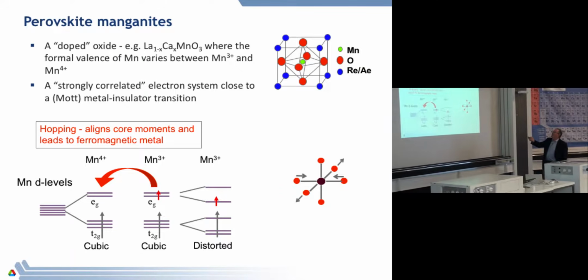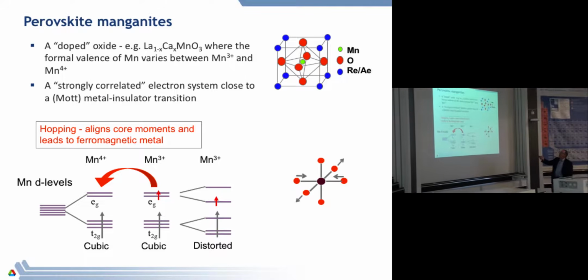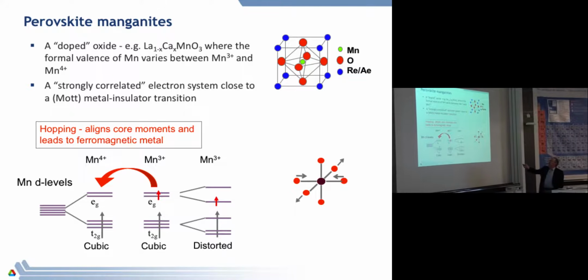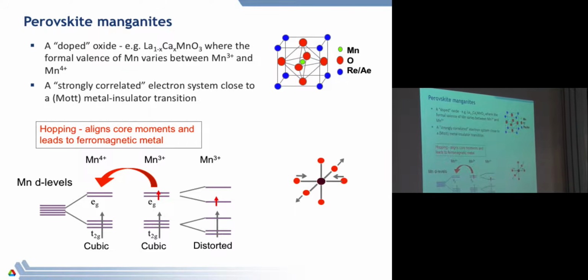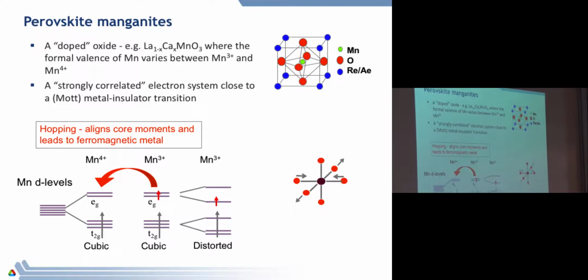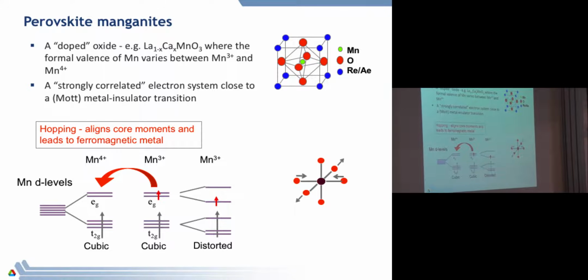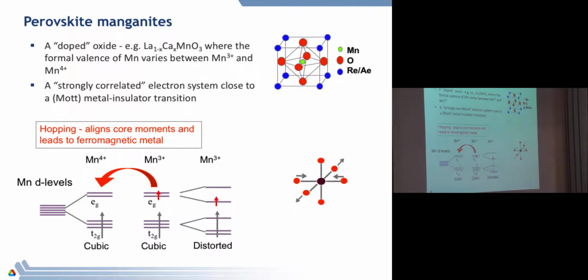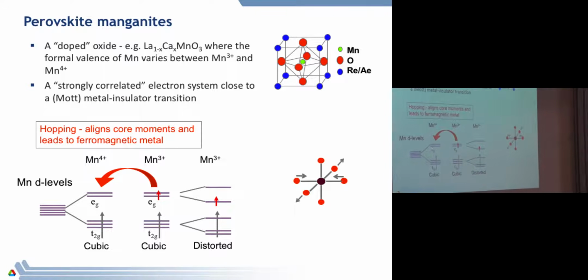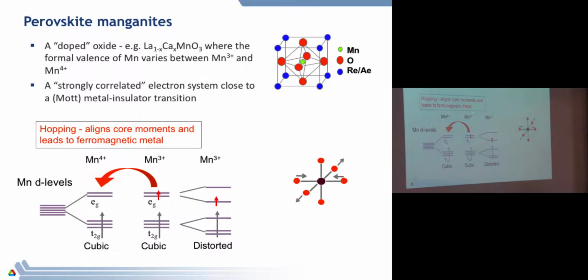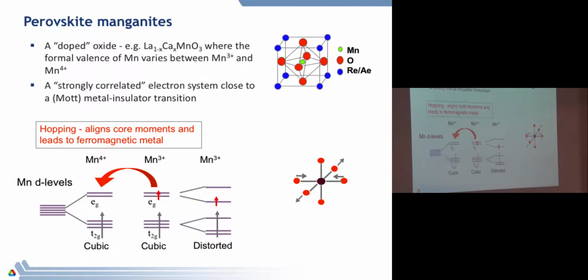Manganites have been studied for a long time, and here I'm just imagining doping in lanthanum calcium manganese oxide. As I go from 3+ ions to 2+ ions, what I do is I turn manganese from a 4+ ion to a 3+ ion. Now a 4+ manganese in a cubic environment turns out just to have 3 electrons lined up at a deep level, and that produces a large local moment, but it doesn't move around. When I add an electron in here by going from 4+ to 3+, I put an electron in this higher energy state. If that electron hops around, because of Hund's rule, if it hops onto this site, it can only hop if the spins are parallel, and therefore the motion of this electron moving around will align the spins, and it means that the ground state is a ferromagnetic metal.